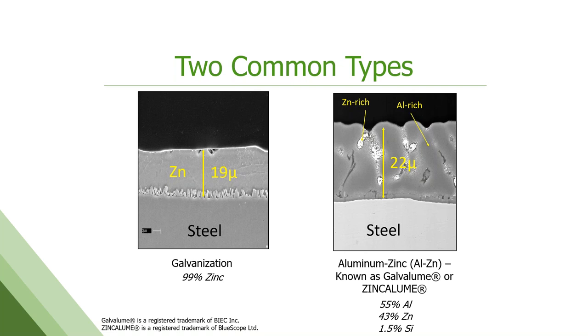The little white areas, tunnels, also known as dendrites, are the zinc-rich areas. So what'll happen once it's out in the field, these zinc areas will corrode first, sacrificing themselves for the aluminum and the steel. And then you're left with all this aluminum still in here as protection, which is a lot because it's so much more by volume.